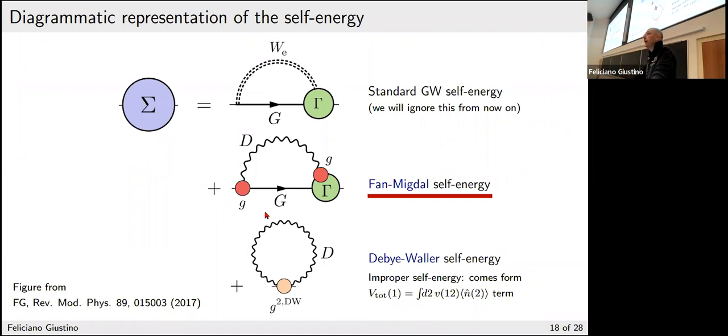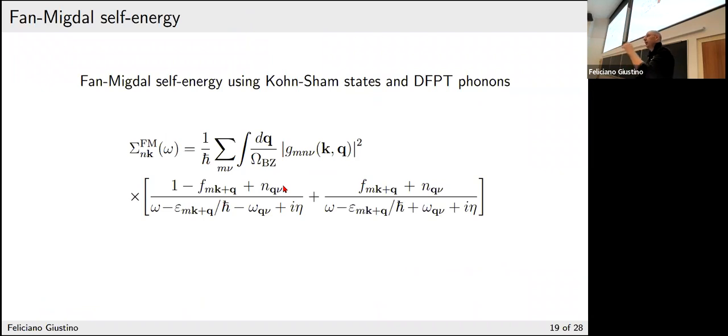That's actually what you're going to calculate during the week on several occasions for standard calculations of electron-phonon couplings, for things like superconductivity, for transport. So that's key to all of it, okay? So basically, you need to do a multiplication of the Green's function of the electrons, Green's function of the phonons, and two matrix elements. So the way it looks, if you get rid of the vertex, you will have a square of the electron-phonon matrix element that you've seen yesterday, all right? Then you have some information about the electrons.